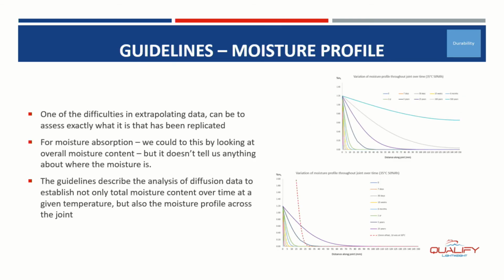So we can predict the percentage of moisture in a joint at accelerated temperatures, but what's actually important is where the moisture is in that joint. The guideline gives the equations that you need to work out what the moisture profile is at a given temperature and humidity over the lifetime of the joint. In this case, we've plotted it all the way up to 500 years and we still haven't reached saturation at the end of the joint.